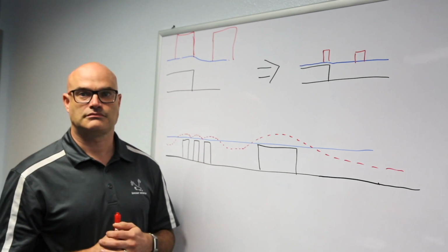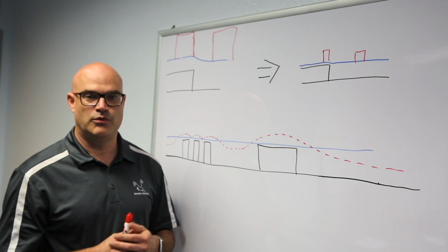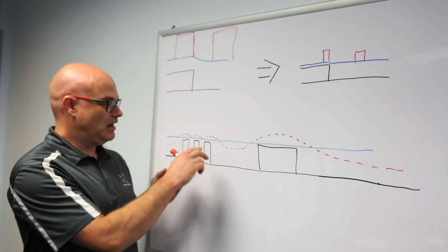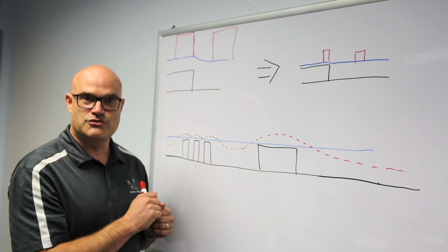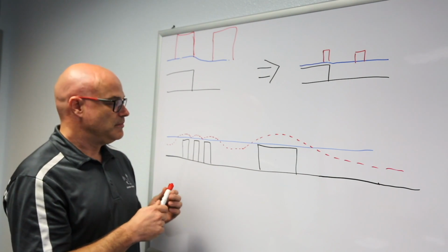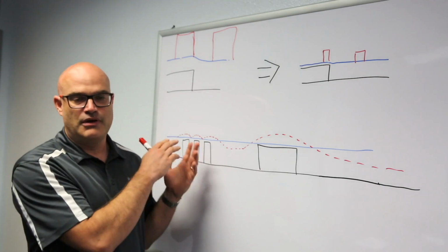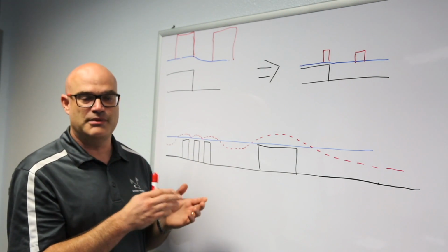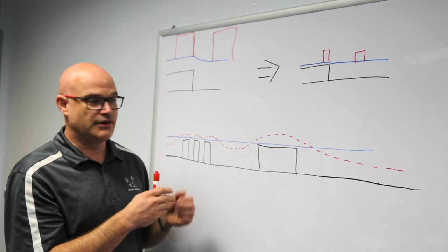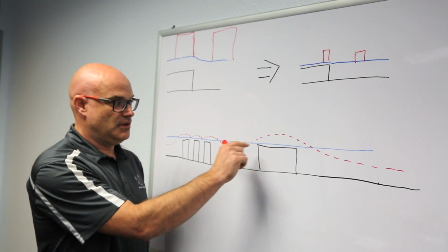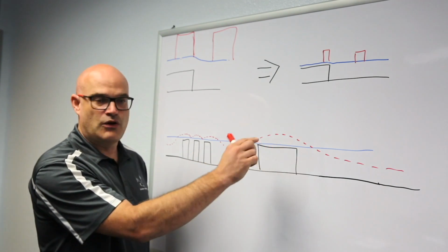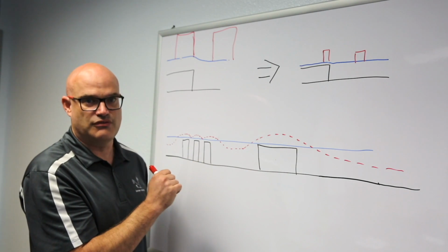So what are some of the challenges you really have to deal with here? Well, when geometries get small, you've got to be able to fill small features without any gaps. But also you've got to worry about the substrate itself now, because we're talking about going from, in the past, maybe 300-400 nanometers down to 100 nanometers or thinner. You're really looking at how the material behaves on the surface itself.